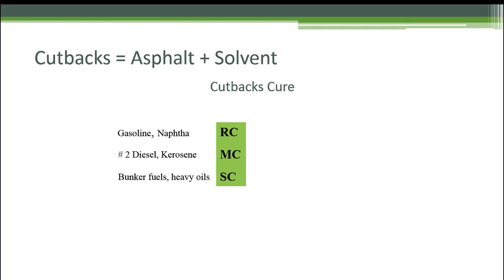So what do we typically use MC for? Prime, right? You know, when you're building a new road and you have an aggregate base down and it's going to sit there for a while and you want to maintain profile and grade and keep it integral, you're going to shoot a prime. And so we use MC, a medium cure cutback, to shoot the prime. So we cover it up with a little bit of residual asphalt before we can pave it. And the classic smell, I mean, you can drive through it and get close, you know that the prime's been shot because you can smell it. You can smell the diesel or kerosene evaporating off.